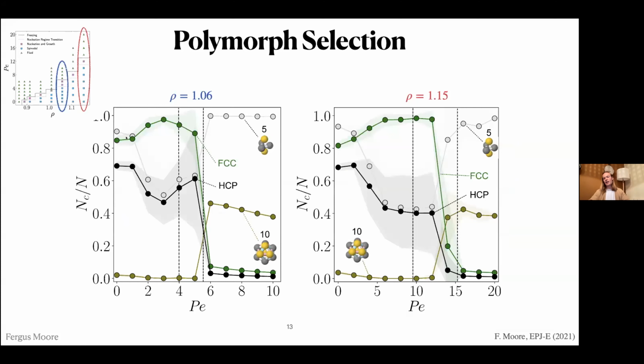So you can see the same graph as before, but I've added another higher density, and you can see it persists at higher density as well, and the amount of FCC actually increases, and you can see HCP going down more drastically. These shaded regions are the standard deviation as we averaged. The final bit of interesting data that comes from this plot is I've outlined with these two vertical dashed lines. And what's happening here is marking an area where the nucleation or crystal growth mechanism is different.